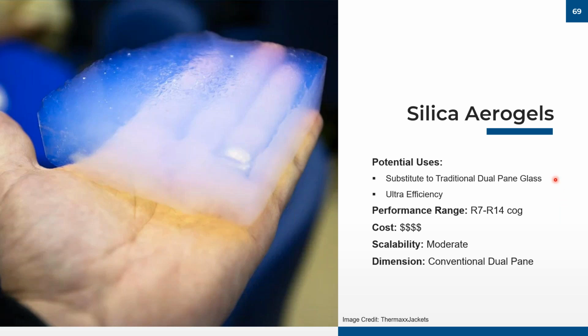So this is a great substitute for dual pane insulated glass, just by adding that silica aerogel to the glass, reaching ultra efficiency. And one factor of this is the efficiency really depends on the thickness of this material. So the thinner the material, the lower performing, and then vice versa. The thicker that material gets, the higher performing that can be. This is still in its infancy. We see this ramping up in scale in the next couple of years. I think even starting mass production starting next year as well.